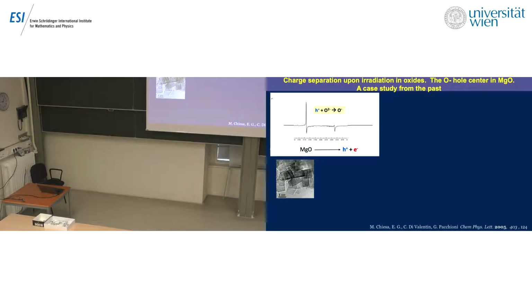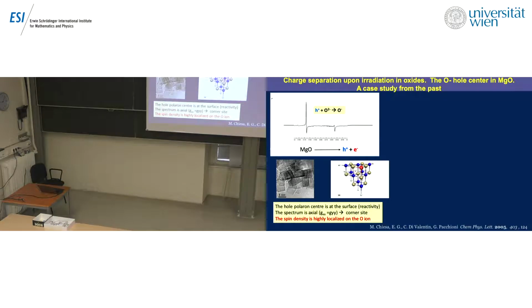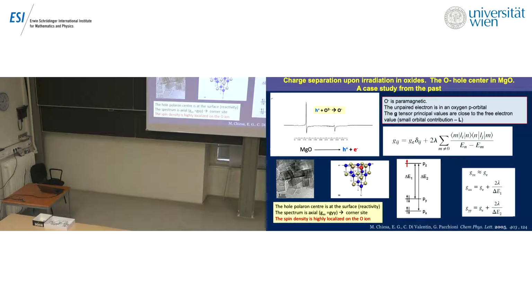If you increase the power, you can get rid of the previous signal of this one. I don't want to discuss this. I did this in the past several times. And you observe the very simple axial signal of this polaron. The symmetry of the signal tells you that the tensor is axial, and since this is a surface signal, there are many elements, reactivity and so on, that tell you that it's a surface signal, so you have to find this hole polaron stabilized more or less here, I'm pretty sure, at this vertex of the crystal, where there is a ternary axis that explains such a kind of spectrum.